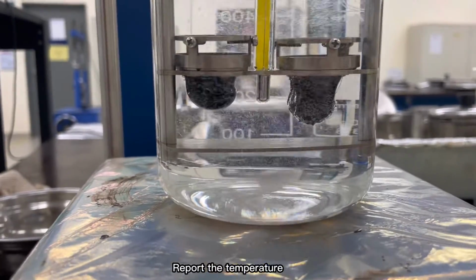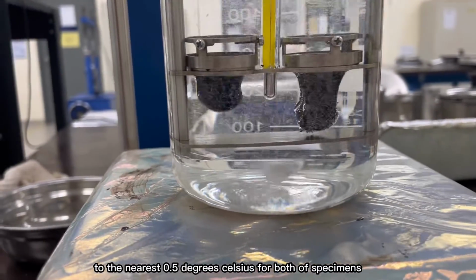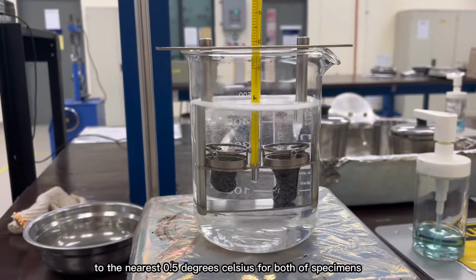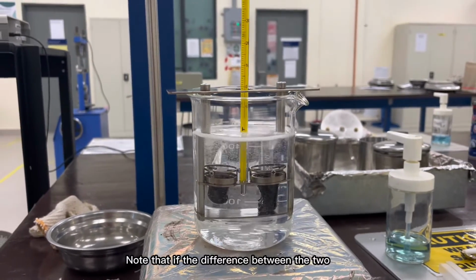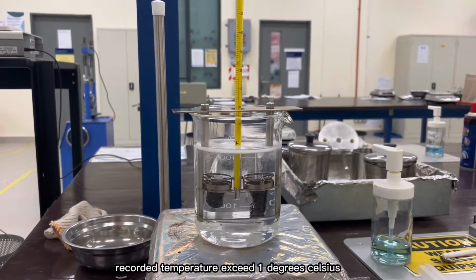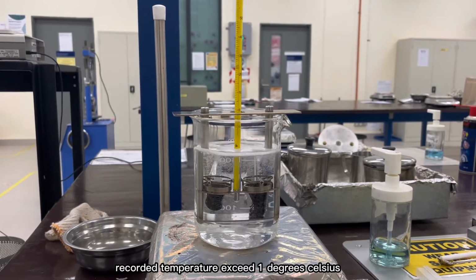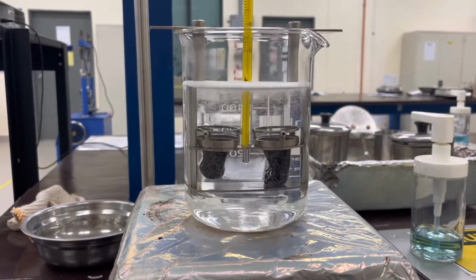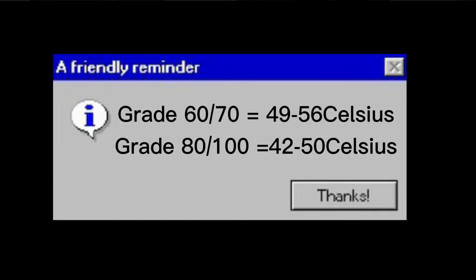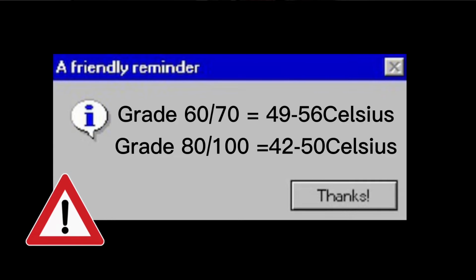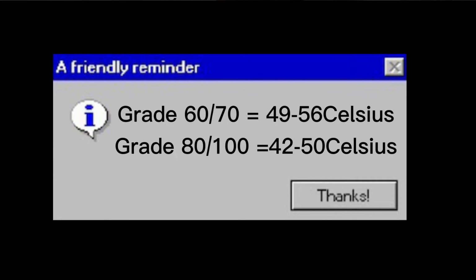Report the temperature to the nearest 0.5 degrees C for both specimens. Note that if the difference between the two recorded temperatures exceeds 1 degree C, please repeat the test. Lastly, the important thing is that the result of the softening point must be in range, by referring to the bitumen grade being used.